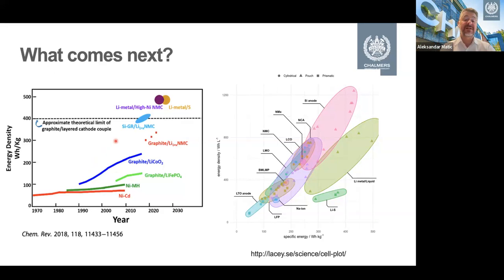For instance, one very straightforward way would be to replace graphite with lithium metal, which immediately would enhance the energy density. You can go to high voltage materials like these high nickel content nickel manganese cobalt oxides. You can go to completely new chemistries like the lithium sulfur chemistry, enabling you to reach maybe towards 500-600 watt hours per kilo. So that means we will have batteries which can drive our cars longer or simply have longer discharge and so on at a certain power.